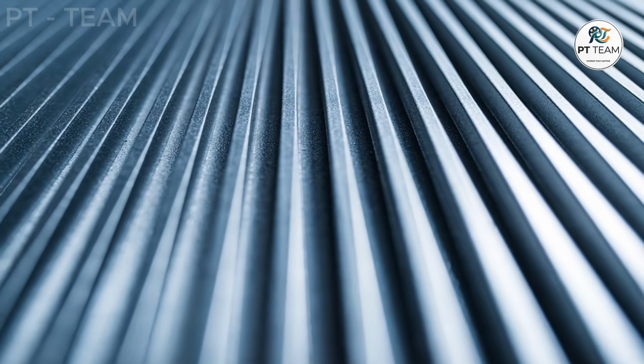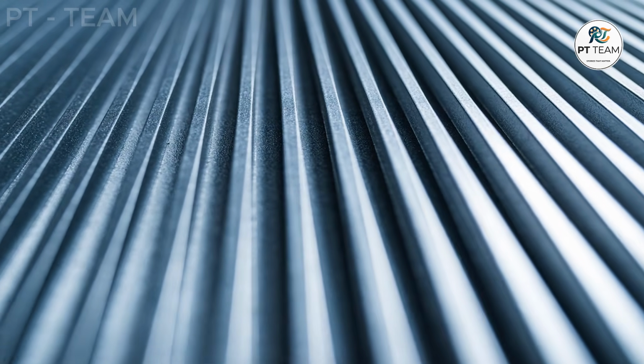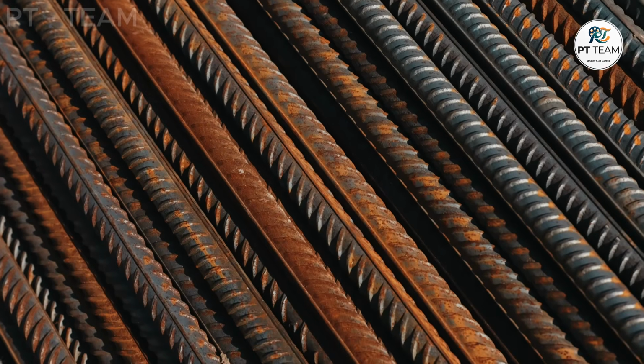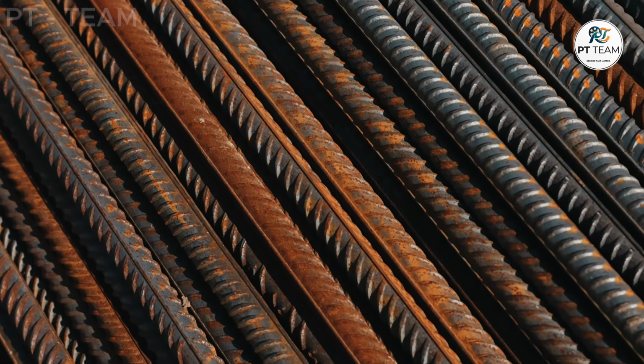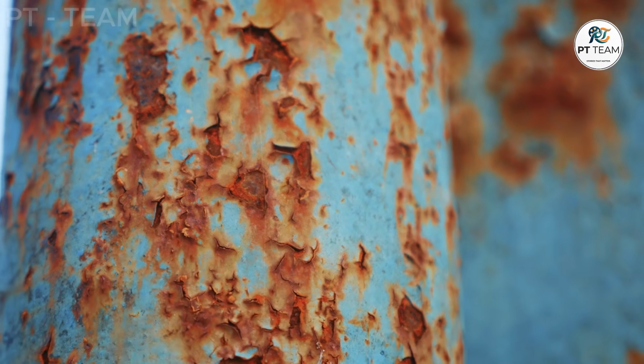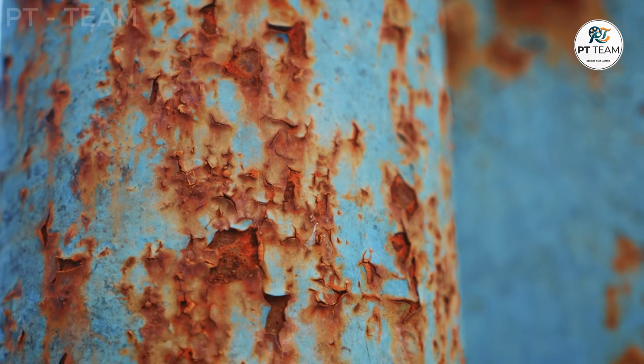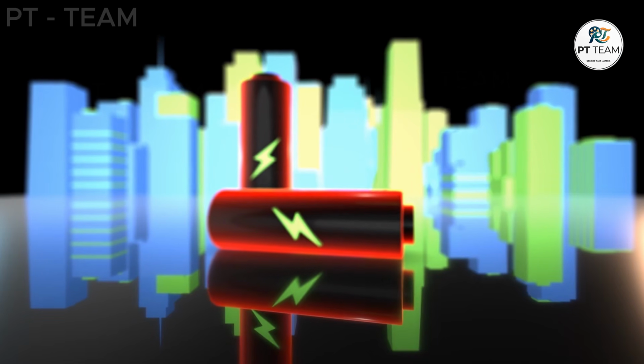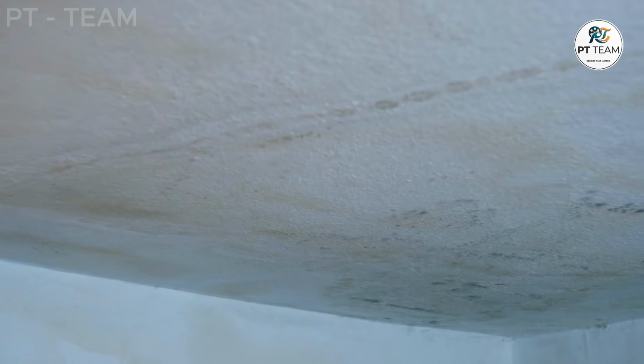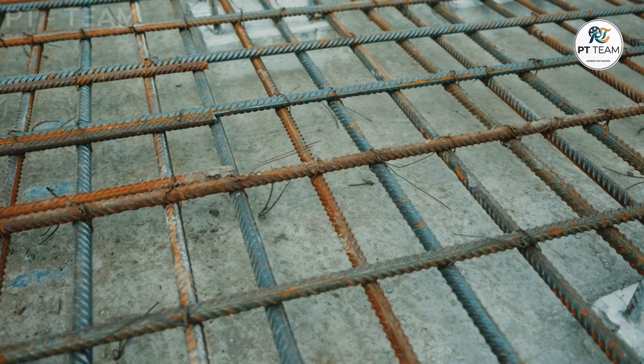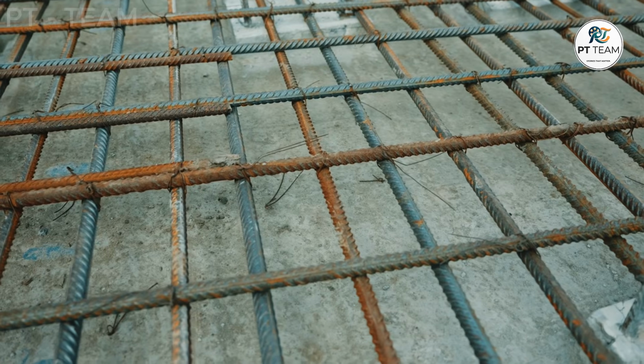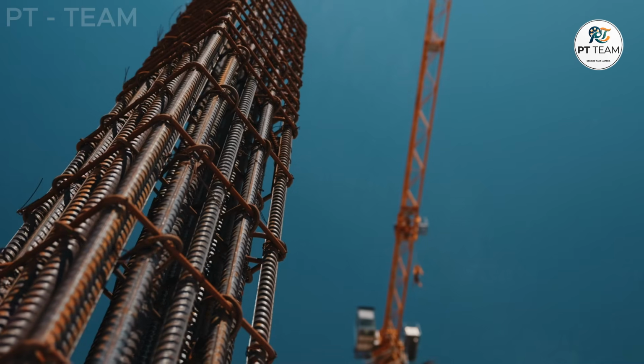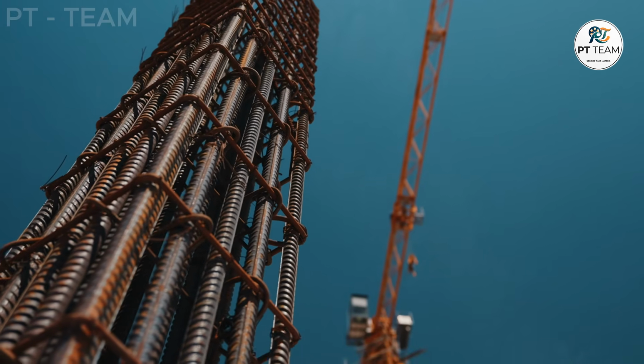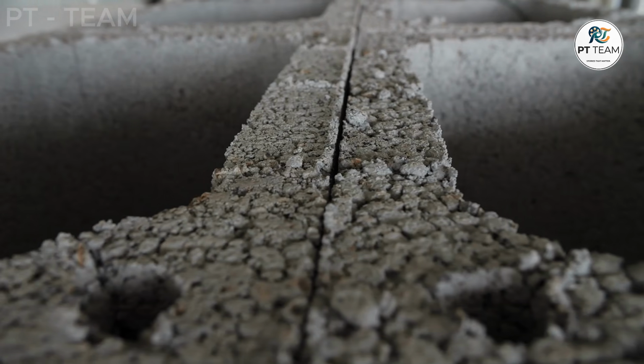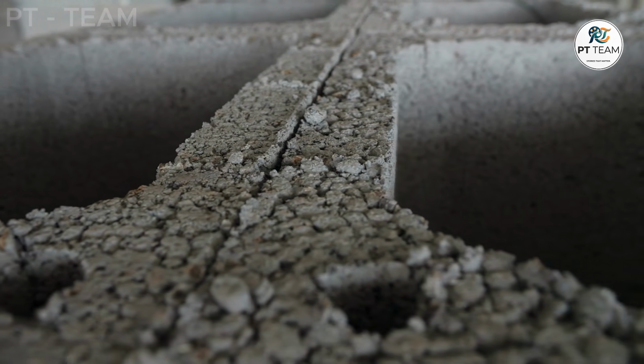Once the chloride concentration hits a critical threshold at the surface of the steel, it locally breaks down that protective passive film. This is the precise moment the corrosion process is initiated. A microscopic electrochemical battery is suddenly formed inside the damp concrete. One specific area of the steel begins acting as an anode, which means it starts actively dissolving and losing pure metal. Another nearby area acts as a cathode, facilitating a completely different chemical reaction.